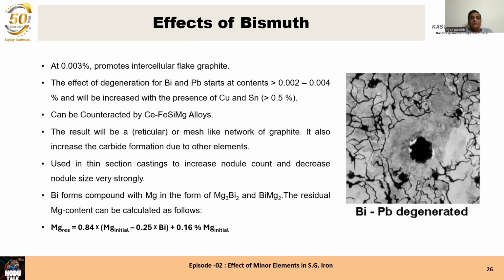Effects of bismuth at 0.003%. Bismuth promotes intercellular flake graphite. Look at the microstructure. In between, the graphite nodule is also deteriorated. It's not fully nodular. And in between these graphite nodules, you have got cellular graphite, intercellular graphite, which is like flakes. The flakes are not sharp, but this is a very dangerous structure to have. Your mechanical properties will be even lower than the gray iron properties.